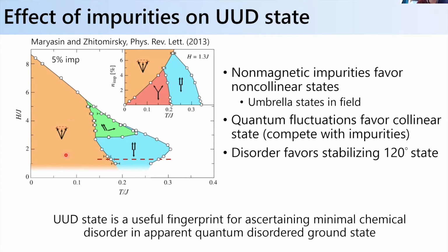It favors non-collinear states. In particular, the addition of non-magnetic impurities seems theoretically, from this sort of Monte Carlo type of analysis, to favor what they call an umbrella state in field, okay? So in other words, the presence of disorder would tend to favor stabilizing a 120-degree state, okay?